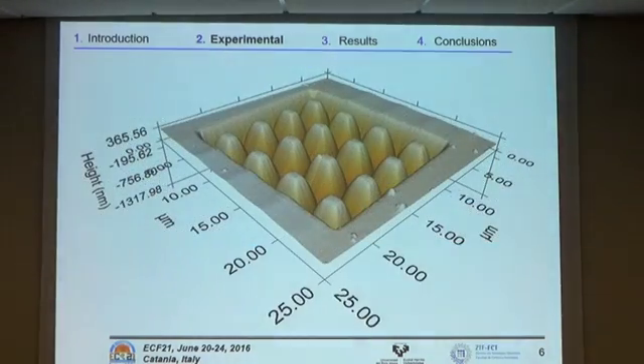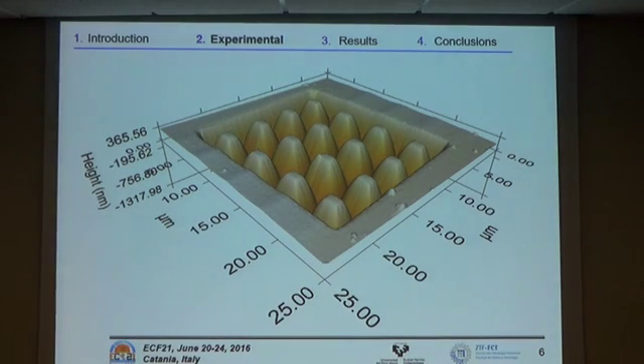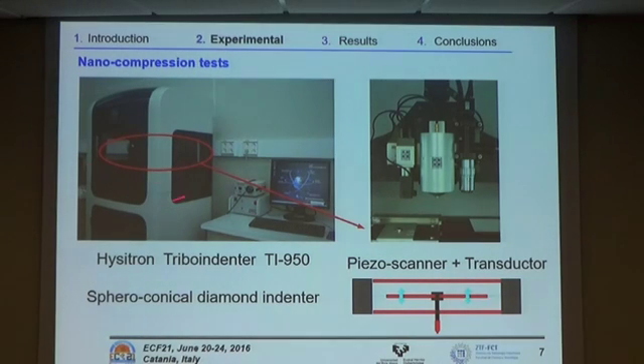And this is how this array of pillars looks when you look at it in the nano-indenter, using it as an AFM machine in contact mode. And so this is how it looks when you look at it in the nano-indenter, which is the main part of the main equipment for this study. This is the Hysitron Triboindenter, TI-950. The main part of this equipment for the nano-compression test is the transducer and the piezo scanner, which is here for small loads, and this is the other one for slightly larger loads. Schematically it is shown here.